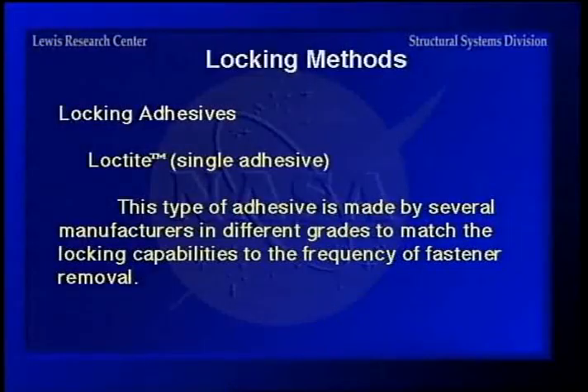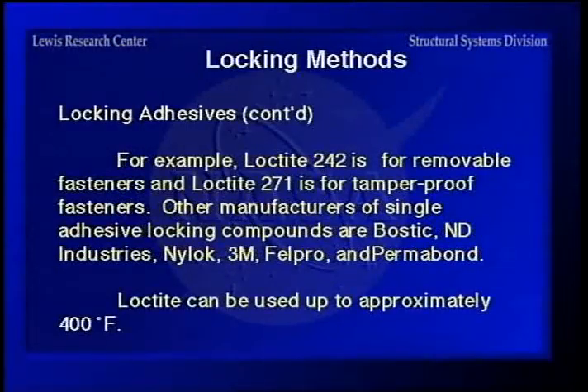Now here's Loctite, which we use around here all the time. That's actually a trade name, but different people make this. It's actually a one component type adhesive that you just smear on the fastener before you assemble it. And it's made in different grades so that if you want to remove the fastener, you use the less sticky type. Like in Loctite, I think 242 is for removable, and 271 is for tamper-proof fasteners, and there's another one or two in between there for bolts that you just want to make difficult to get off. Other manufacturers of this are Bostik, ND Industries, Nylock, 3M, Felpro, and Permabond. And Loctite is good up to about 400 degrees.